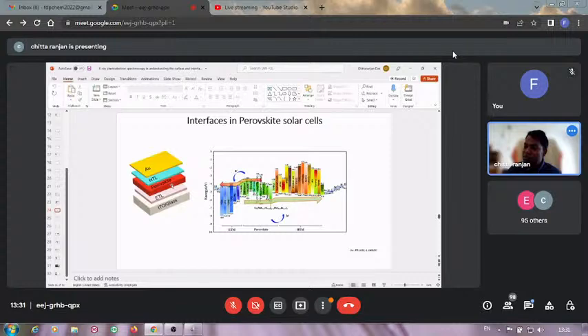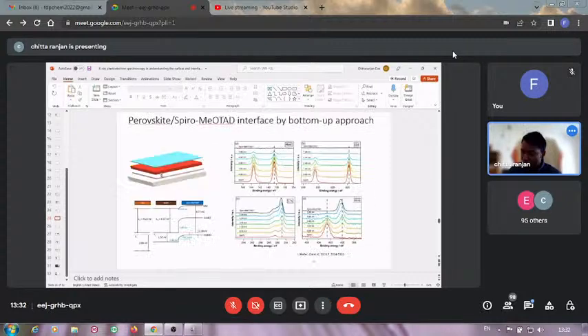So for example, in a study we did, we have a perovskite layer, and then we deposit layer by layer a hole transporting layer, that's called spiro-OMeTAD, which is a P-type semiconductor. You can see the carbon intensity increasing when you keep on depositing, and the nitrogen intensity here is decreasing, and so on. The iodine and lead intensities are decreasing. That means we are not able to see the iodine substrate anymore. This substrate has lead, iodine, carbon, and nitrogen. So after putting, let's say, 10 nanometers, I am not able to see it. And if I put more, then I don't see anything other than the spiro.